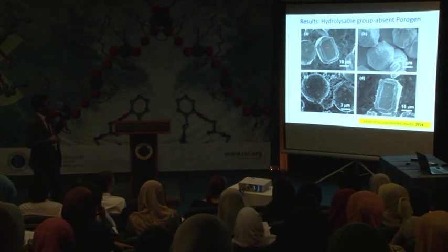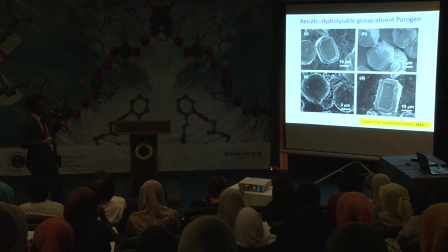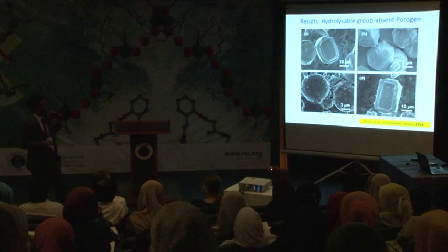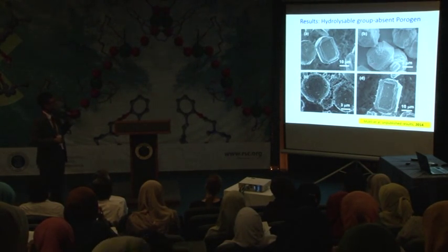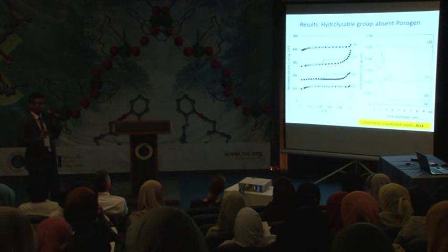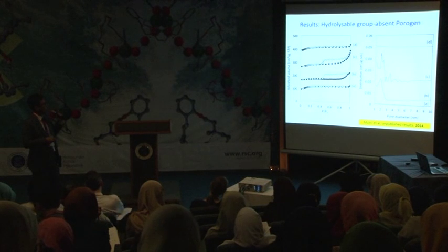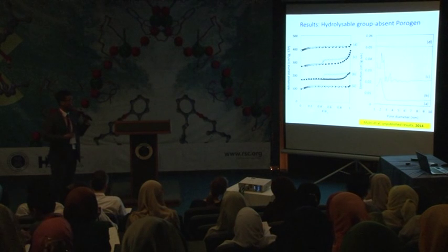When you increase the concentration of surfactants, in the middle of the concentrations you get a different morphology compared to the low and high concentrations of surfactants. This morphology is believed to have a hierarchical porosity. Indeed, from the nitrogen adsorption experiment, we see that the middle concentration of surfactant has a type IV isotherm, showing capillary condensation forming the mesoporosity.